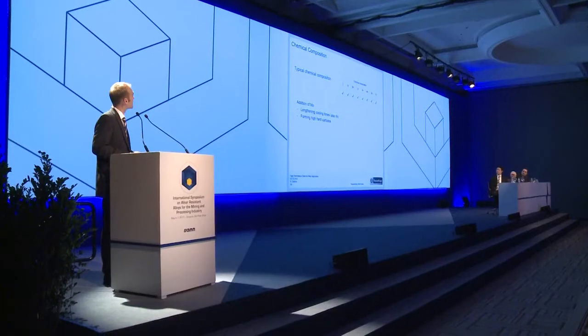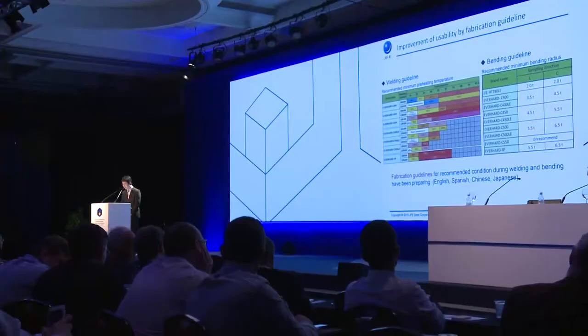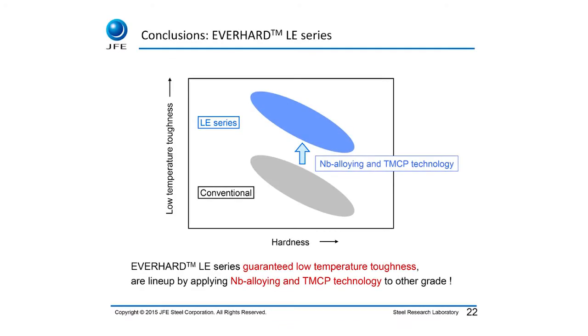The important concept of effective grain size or packet size of the martensite was explained by various authors, and how the best toughness could be obtained by ensuring packet sizes of less than 10 microns. As noted previously, high hardness is usually associated with lower toughness, but the use of niobium to refine austenite grain size prior to quenching and subsequent thermal processing permits superior combinations of hardness and toughness to be realized. This, as we learned earlier, is the secret to the provision of optimum wear resistance.